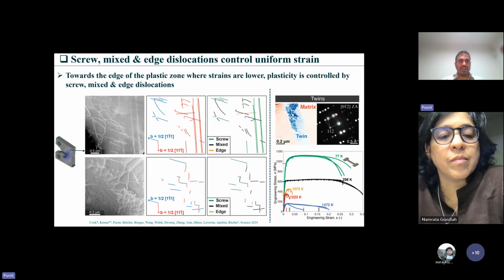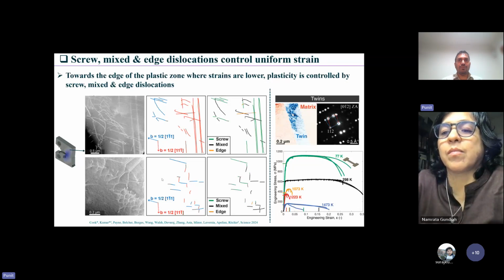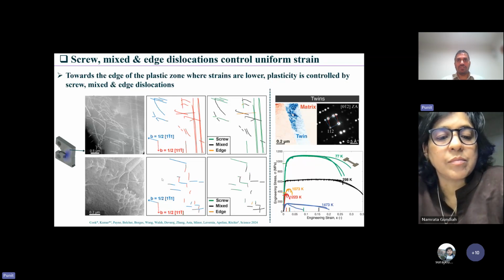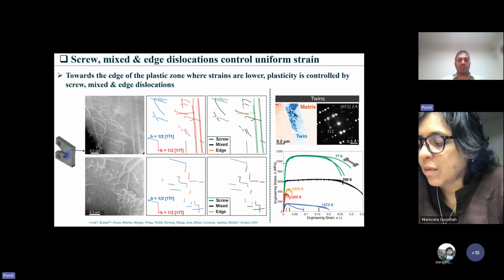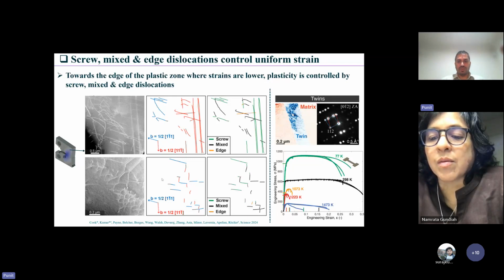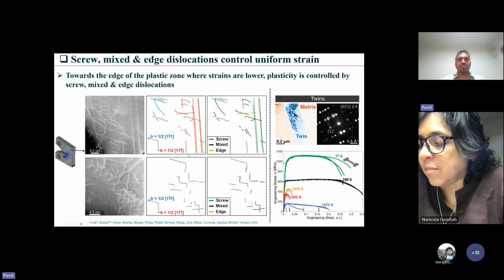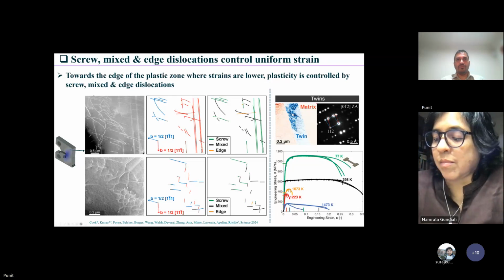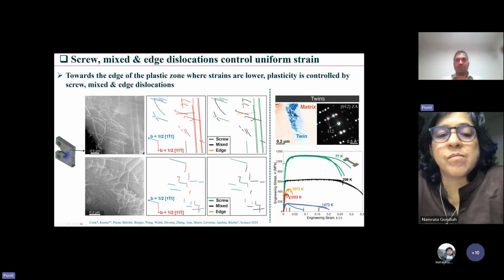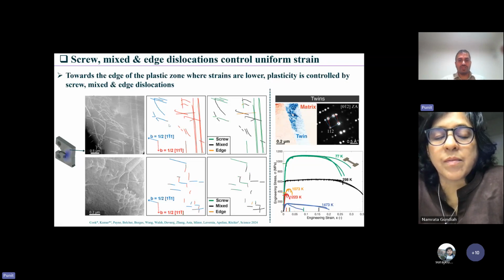If you do TEM and you want to identify which type of dislocation it is, you have to do this g dot b analysis, which is really involved, where you have to tilt the samples at multiple angles and try to identify the Burgers vector of these dislocations. Because of that, we were not able to do the analysis to comment on the statistics of the amount of edge, mixed, or screw dislocation types. But we do see these long screw or edge dislocations somewhere, but we cannot comment on the statistics of how much of which forms.